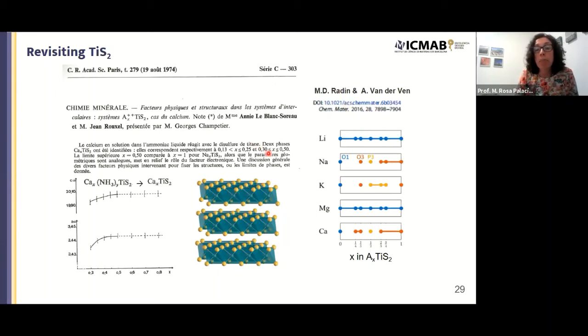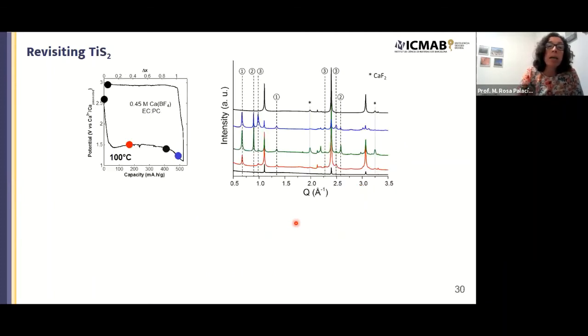Then, apart from that, there was also a paper by the group of Anton van der Ven in Santa Barbara who computed phases which would have different ions between the layers: lithium, sodium, potassium, magnesium, and calcium. And he was computing also which would be the most stable coordination for those ions. And in the case of calcium, it would be either octahedral or prismatic, they suggest, depending on the amount of calcium. In our hands, we took TiS2, we reduced and reoxidized in calcium cells.